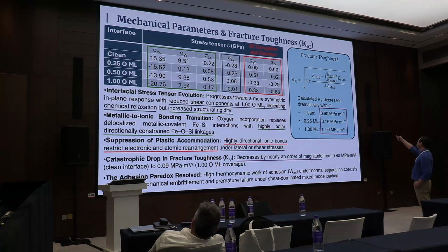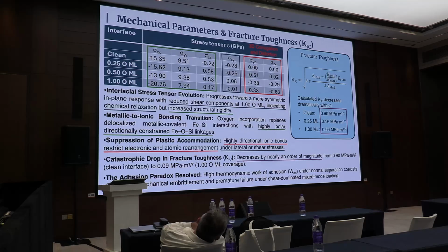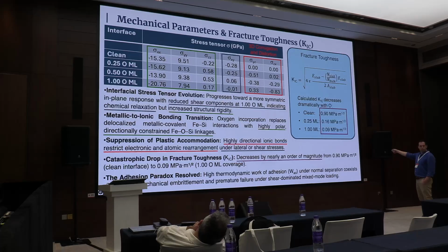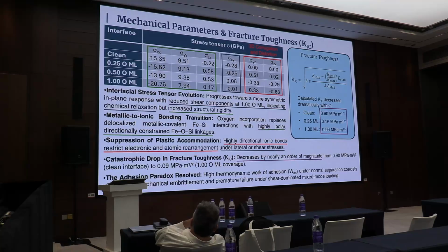And then we compute the fracture toughness, that is saying how far or how easily a hole propagates. You know, you make a hole and the hole propagates. Yeah, the propagation of the broken situation. So how far, or how rigid, is the system in this? We found that from not having any oxygen to having a full monolayer, it decreases by an order of magnitude. So it's easier to propagate the break along the surfaces in that direction. So it's confirming even more that the experiment of Carlos is right. So yeah, this was all.